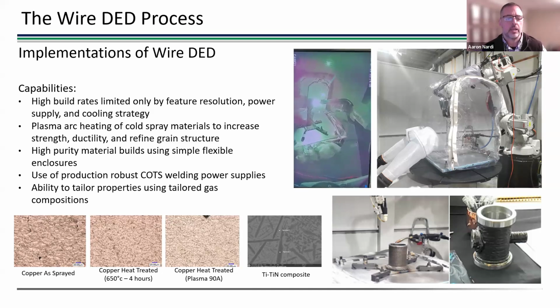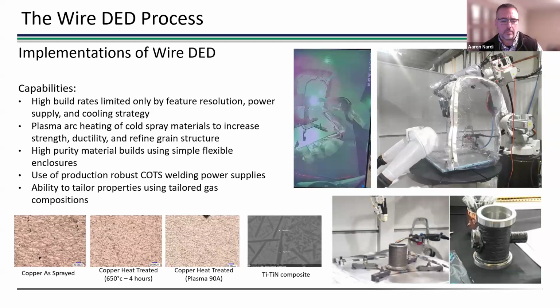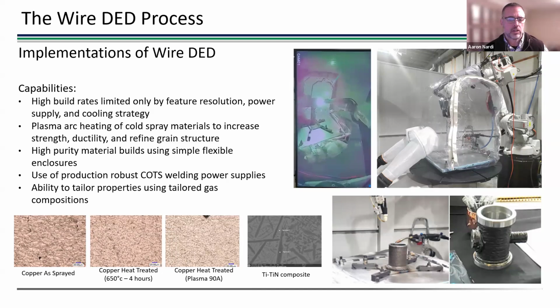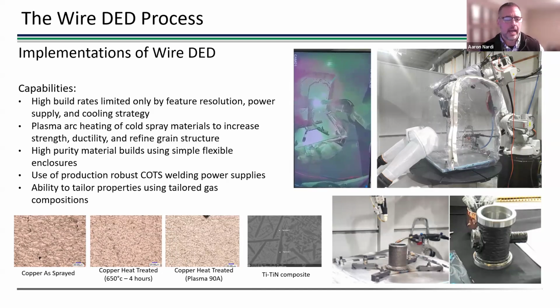And then the third image is actually an example of a plasma heated copper. So in this case, we're actually using the plasma, as many researchers use a laser to process the cold spray, either in situ or ex situ. And then the fourth image there is another variation on what you can do trying to tailor properties.